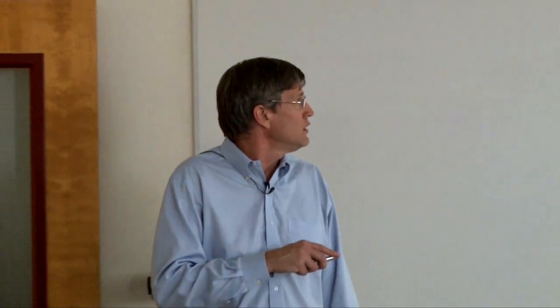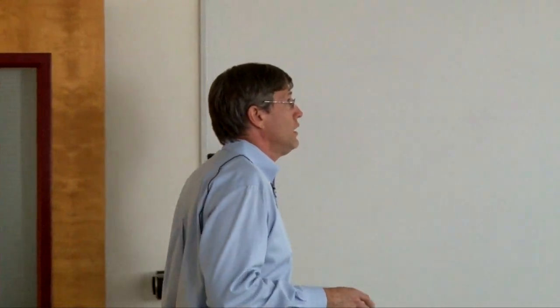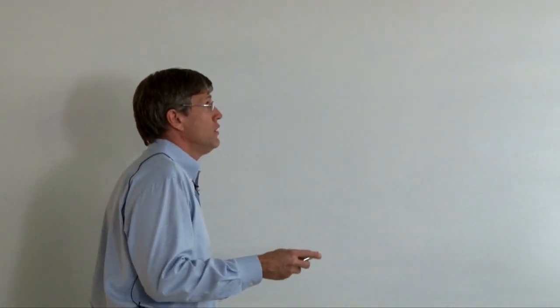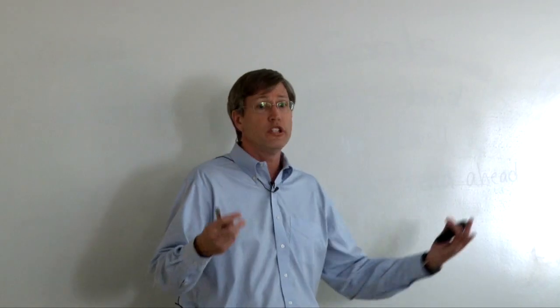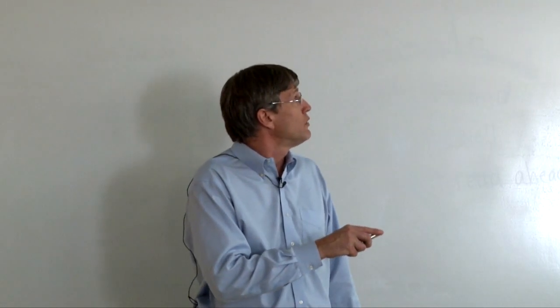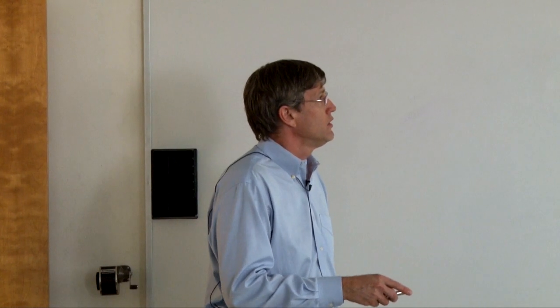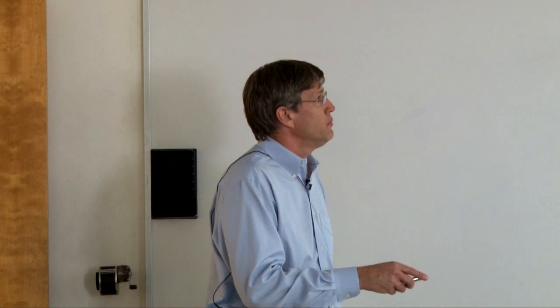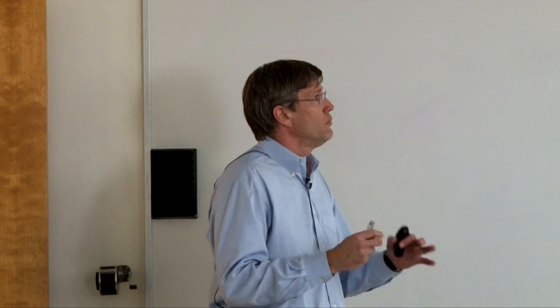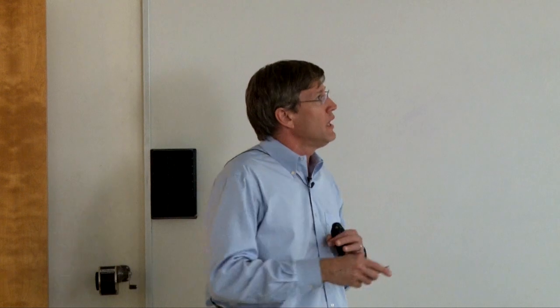So we decided to look at these low frequency acoustic lattice phonon modes. Let's say we reasonably consider that maybe we'd have 3 dominant bands within this region. And so we decided, well, let's see if this analysis holds. Let's look at this second peak. This was a lattice phonon mode. It's a long-range kind of interaction, restricted translations here. And so this told us there's some information about how water interacts with this single sheet.